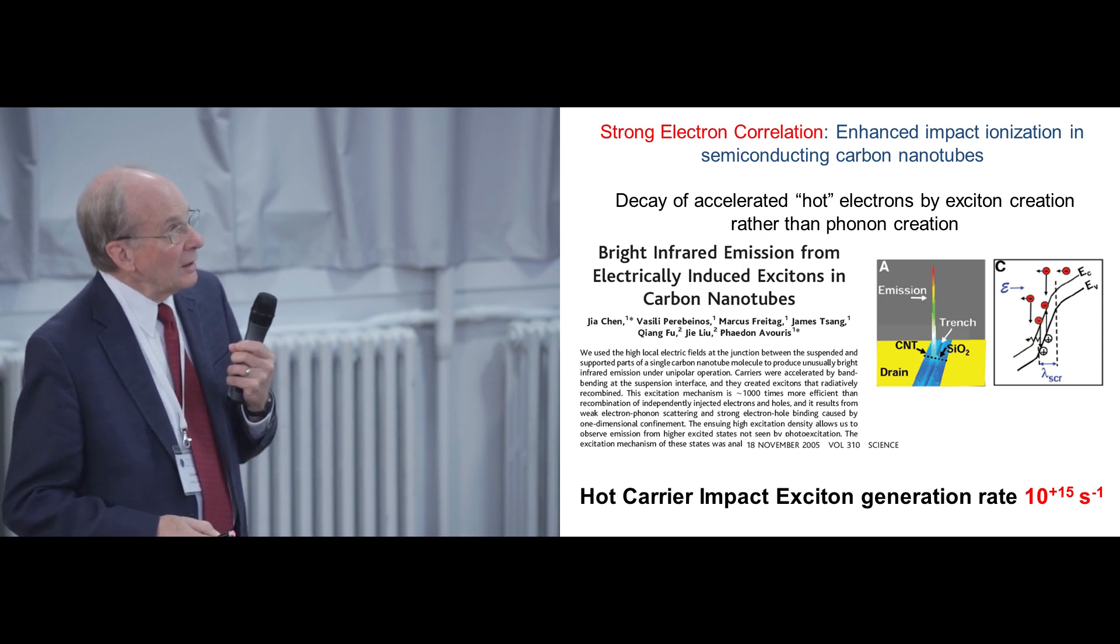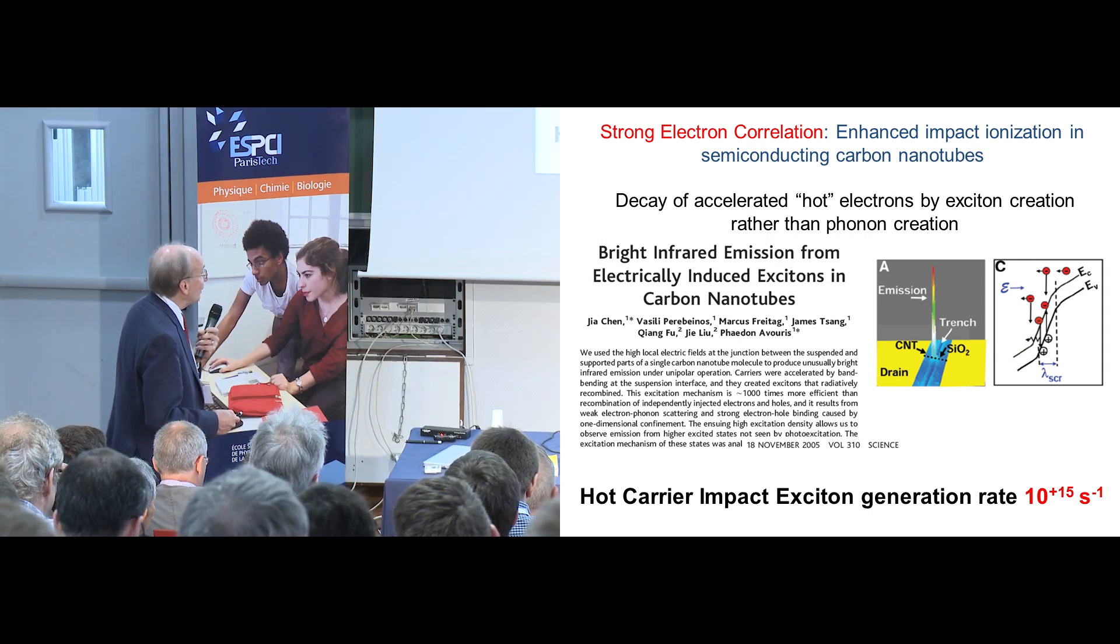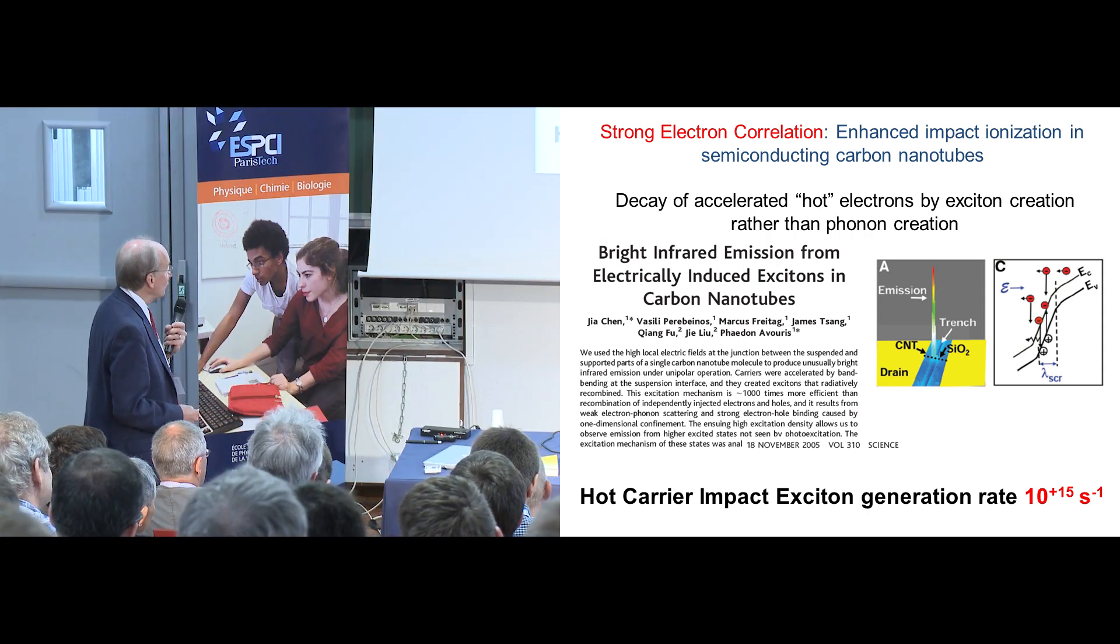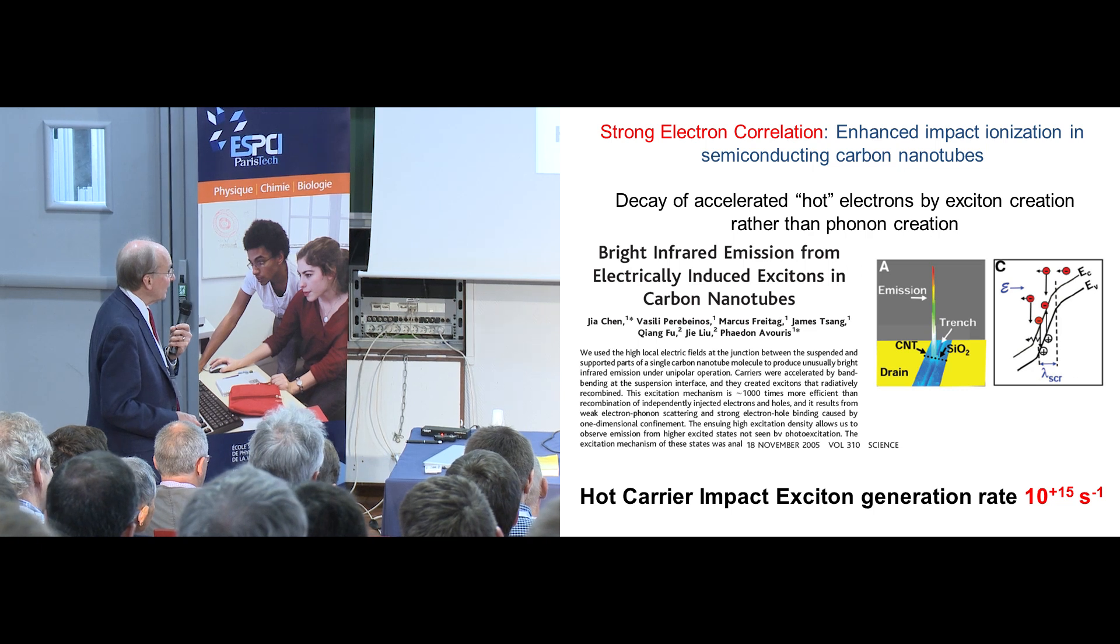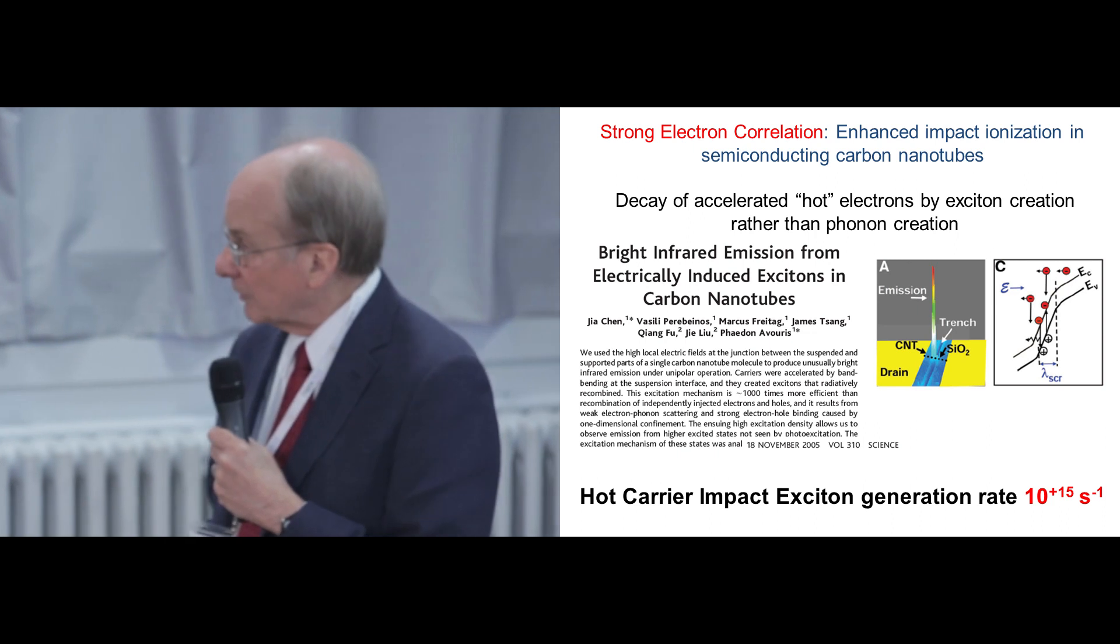So the experiment was that you lay a carbon nanotube across a source and a drain and apply a small voltage here. You can inject an electron into the conduction band on one end and it accelerates, and as it gets higher and higher above the conduction band edge here, it reaches the point where it can relax to the edge in one step by creation of an exciton. This was extremely strong. He actually calculated theoretically as well, the rate was 10 to the 15th per second.